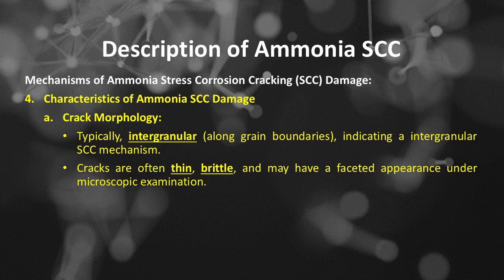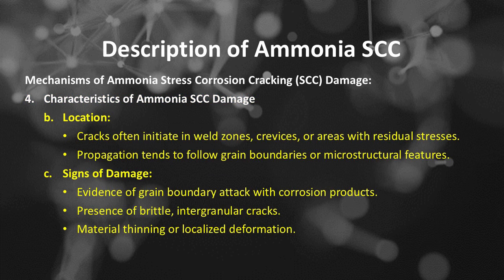Number 4, characteristics of ammonia SCC damage. Crack morphology is typically intergranular, along grain boundaries, indicating an intergranular SCC mechanism. Cracks are often thin, brittle, and may have a faceted appearance under microscopic examination. Location: ammonia stress corrosion cracking damage often initiates in weld zones, crevices, or areas with residual stresses. Propagation tends to follow grain boundaries or microstructural features. Number C, signs of ammonia stress corrosion cracking damage: evidence of grain boundary attack with corrosion products, presence of brittle, intergranular cracks, material thinning or localized deformation.